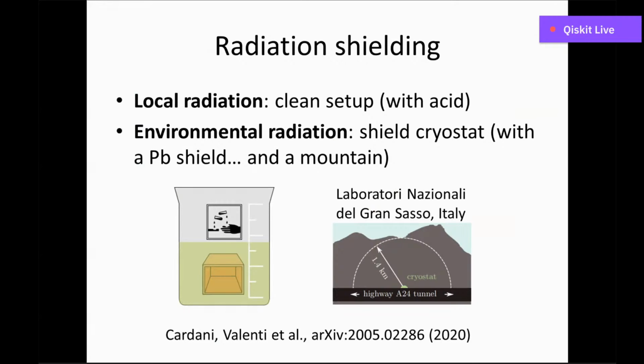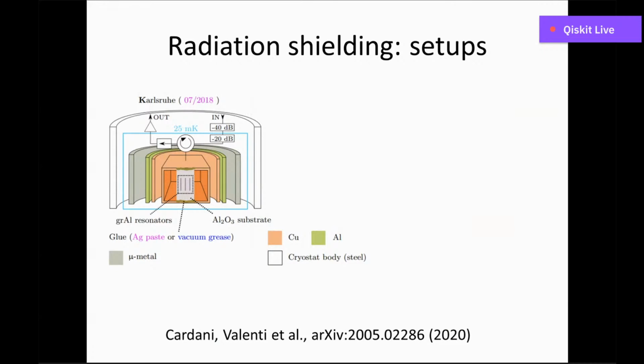To test this, we made measurements in 3 setups. The first setup is the cryostat in Karlsruhe Institute of Technology, which is our control setup, meaning it was not cleaned and not shielded. As we can see, our granular aluminum resonators are sitting on the sapphire chip, which we glue to the waveguide either with silver paste or vacuum grease, depending on the setup. In this one, we used silver paste. And the waveguide is then surrounded by a copper aluminum sandwich and a mu metal barrel inside the mixing chamber. This is a magnetic shielding.